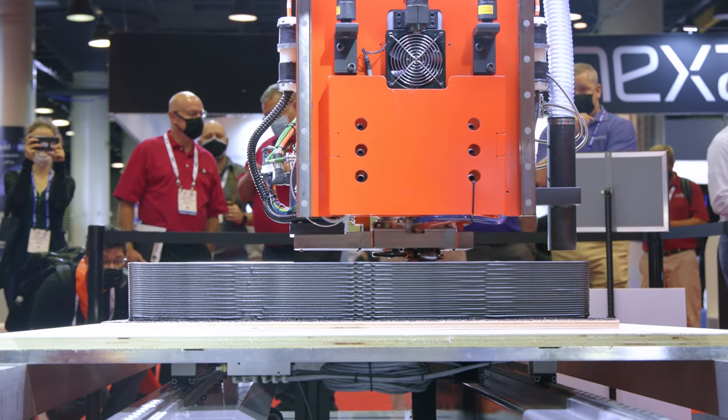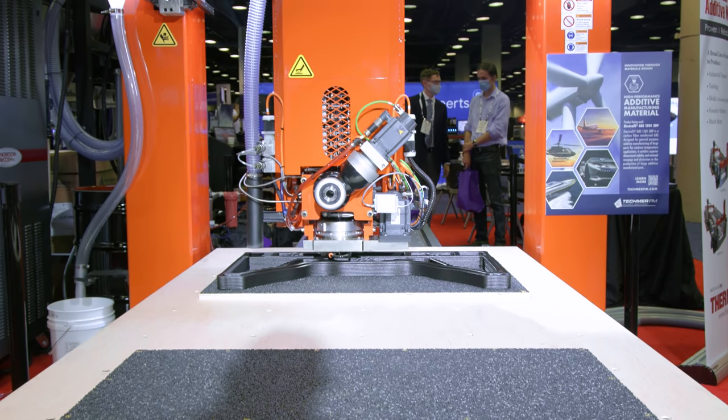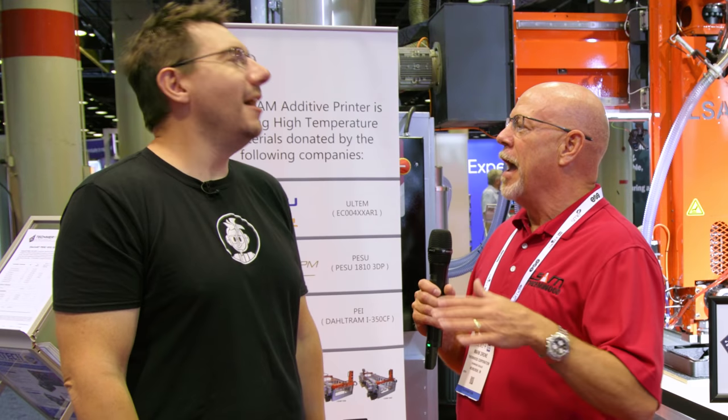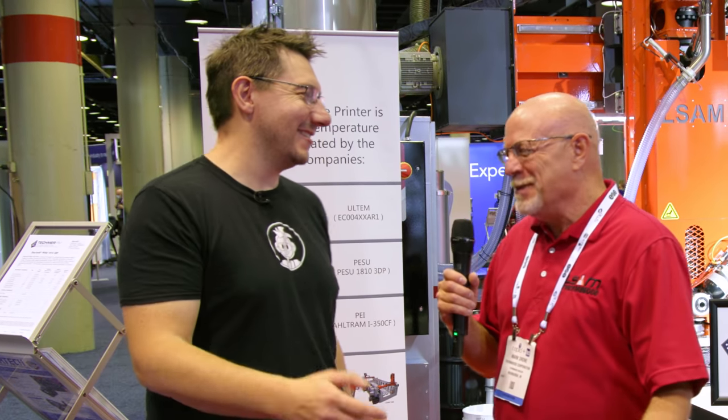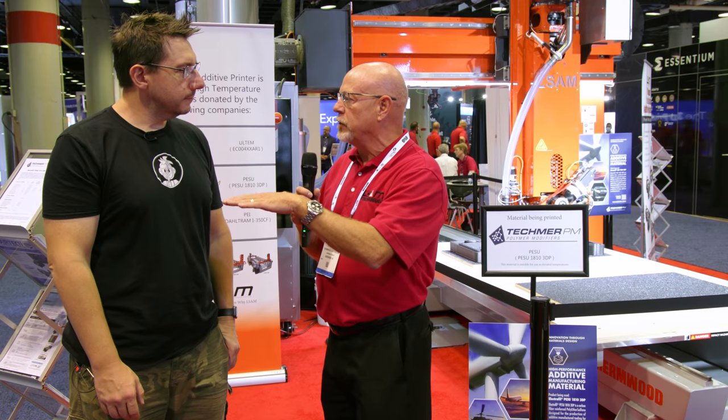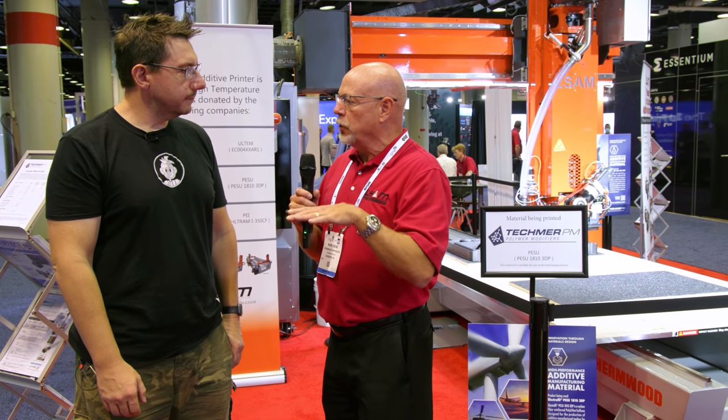And then you're printing, it looks like, on plywood? Yeah, with sandpaper maybe? No, it's something we had to develop when we started into this business. It's what we call a bead board. A bead board. We tried a number of different platforms to print on, and this seemed to work the best. It's basically just ABS pellets, and we use this proprietary glue. It's basically wood glue. It's proprietary, but you just told me what it is. That's all right. We spread that on and put the ABS pellets on, let it dry, of course. What helps us there is that as you're laying down the raft layers of beads, you're actually melting the ABS pellets a little bit. Okay. And you're also liquefying the glue.